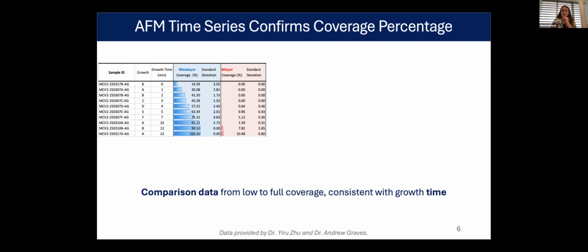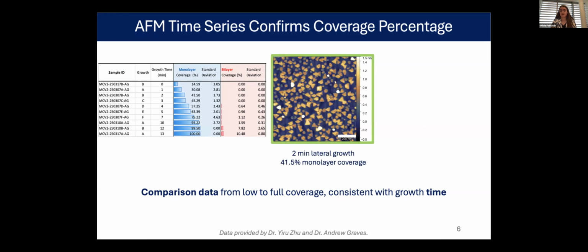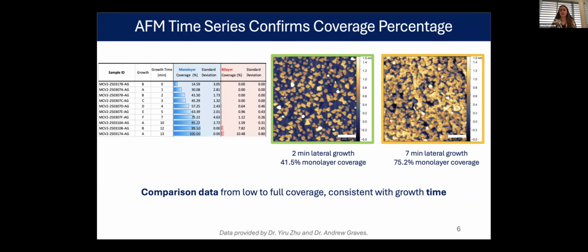So we confirmed this by using this time series data where tungsten diselenide was grown for various amounts of time. In this table, we go from 0 to 13 minutes, and that was enough data that for each time, you get a different coverage, which we then confirm with AFM what that percentage might be. So then we can understand how the sample, the monolayer, grows and covers the substrate as a function of time. So we can calibrate and make sure that we're getting kind of reliable data.